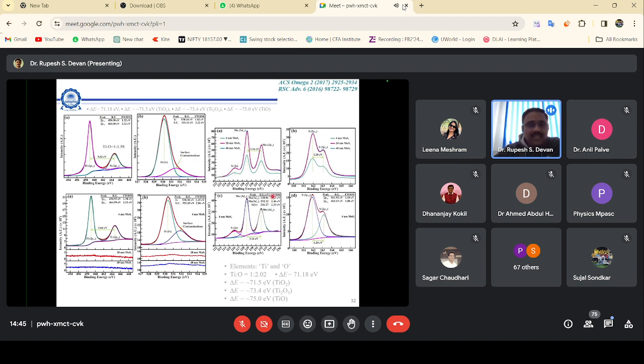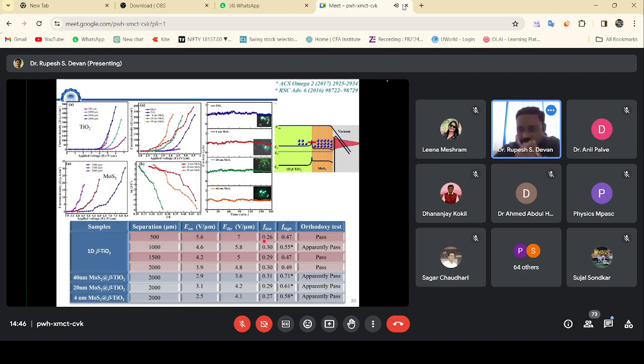Now, if you look at the signals relative to Mo and sulfur, then you will realize that when we are on the 4 nanometer layer, the Mo signal and sulfur signal are down because the layer was just 4 nanometer. But when we move to 40 and 20 nanometer, then obviously 10 nanometer was scanned, so you can see the signal remains almost constant. And then further thorough analysis gives the information that MoS2 and TiO2 remain in their own nature rather than forming impurity phases at the interface.